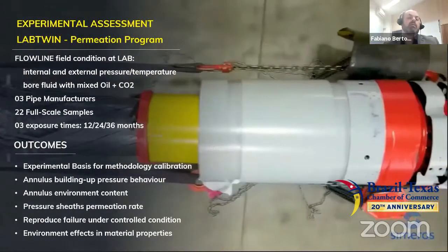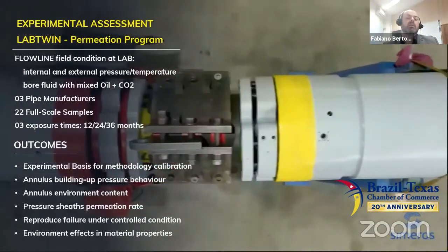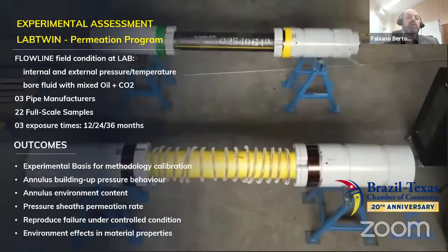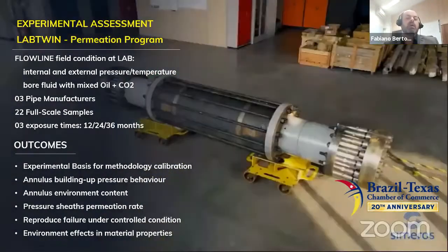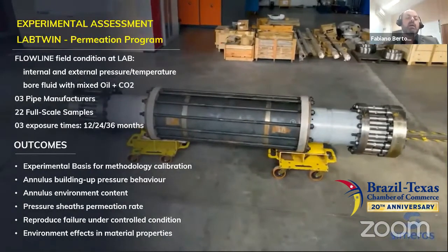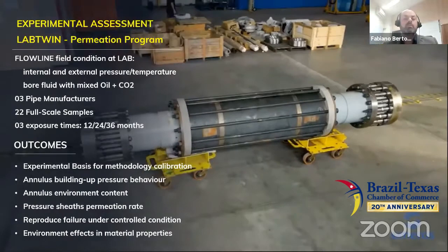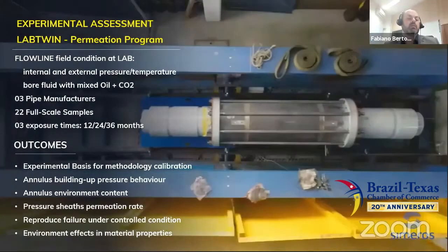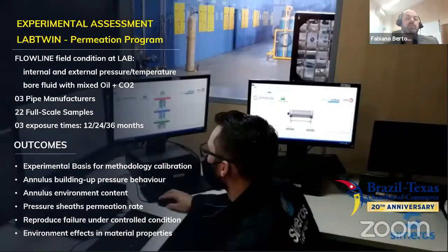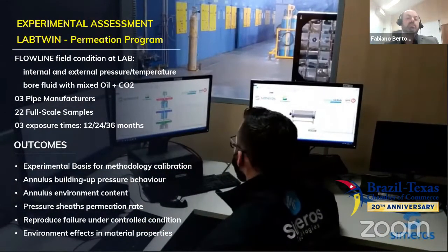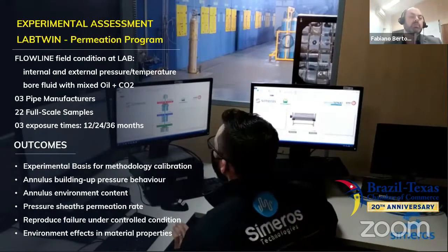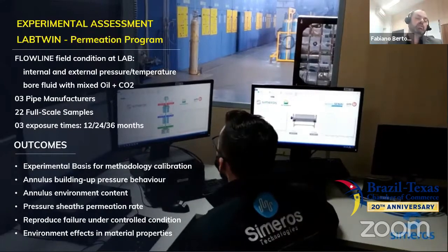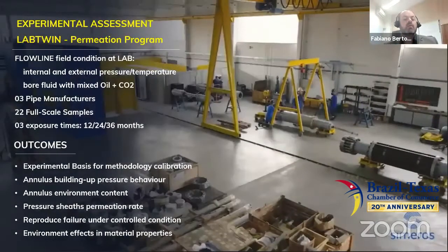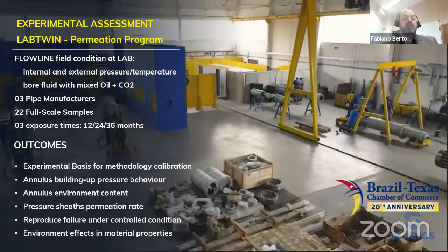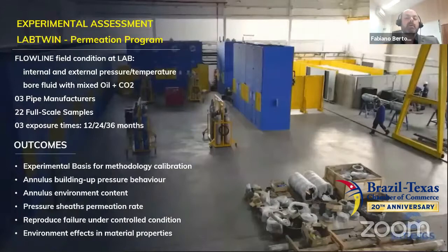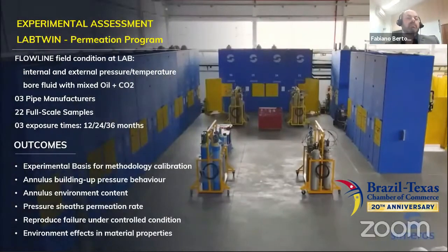expected results. The most relevant outcome is related to the generation of experimental basis to calibrate permeation models based on annulus building up pressure behavior, annulus environment content throughout the exposure time, and pressure sheaths permeation rate. Additionally, the project aims to reproduce the SCC CO2 failure mode in lab under controlled conditions from initiation until failure. Finally, an evaluation about the effect of the harsh environment in the pipe layer material in different aging levels will be done.